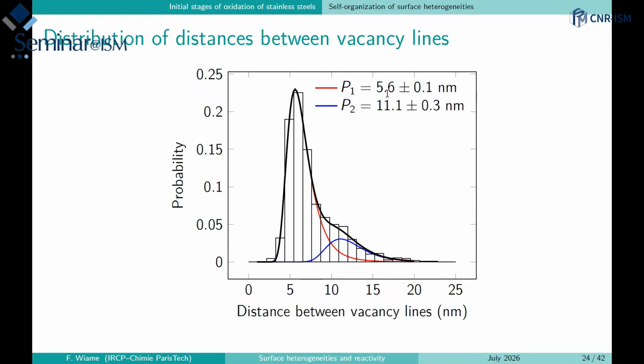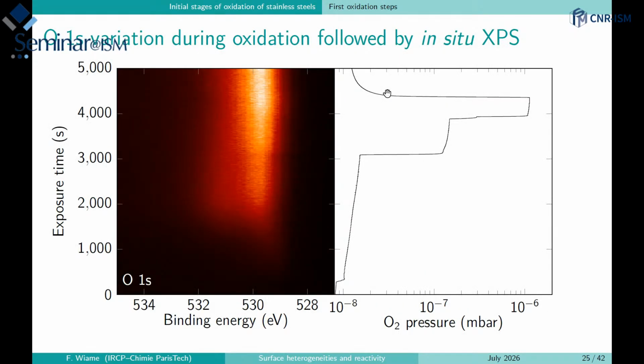In fact, this is really due to the fact that there are different mechanisms of relaxation. The first one being the vacancies, another one being a change in the local composition, and also sometimes you can have a relaxation of the stress which is not made by changing the structure, but by changing the composition at some place. And this is the reason why we have this two-mode distribution of vacancies.